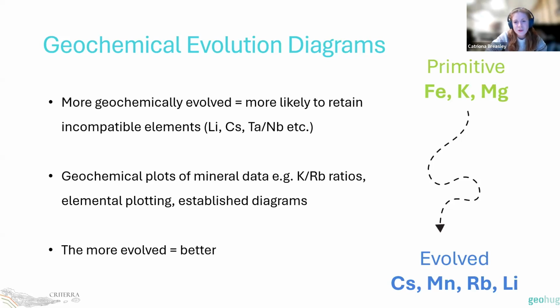You can take the geochemical points of your mineral data and plot them against some established diagrams in pegmatite literature, such as the potassium and rubidium ratio versus your incompatible or compatible element. This should show your nice linear trends, which can help inform on your paragenetic sequence. You can simply plot elements against one another to show similar trends. And there are some established diagrams in literature, which I'll go on to talk about a little bit later. And again, the more evolved, the better, because the more likely you are to have enough lithium content in your melt in these really geochemically evolved systems to crystallize pegmatites that you want to target for mining.